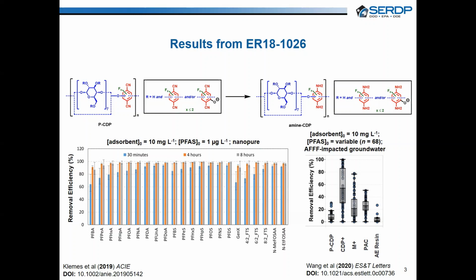We evaluated the performance of this cyclodextrin polymer to remove a mixture of 22 PFAS from water. And what we found was really excellent performance, as shown in the bottom left of this slide, with nearly all of the PFAS removed in under 4 hours of contact time, which is really remarkable performance with an adsorbent dose of only 10 milligrams per liter.